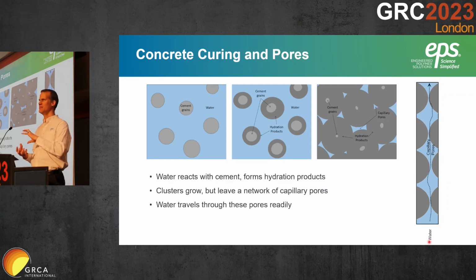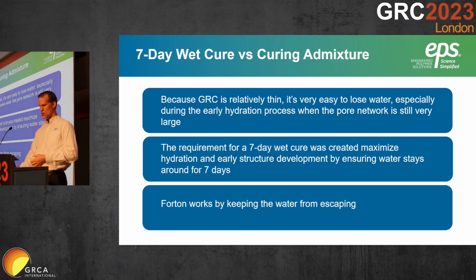The larger these pores are and the more connected they are, the easier it is for water to move through the system. So when you demold GRC, it's typically after about a day. At that point, cement, as you know, isn't completely hydrated yet. Those pores are still fairly large. At that point, it's very easy for water to move through these networks and evaporate. To keep that water in there, there's the 7-day requirement for a 7-day wet cure to make sure that there's constantly water around for cement to hydrate with.